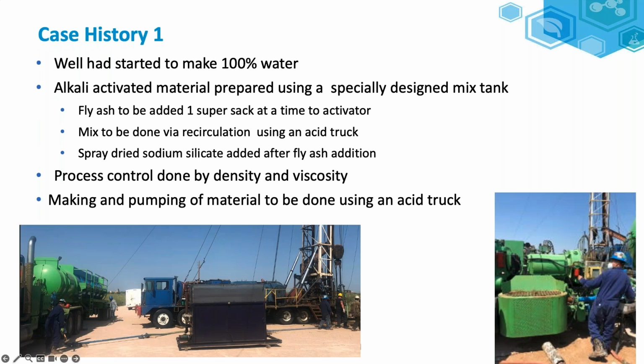The cost of the raw material was a bit more than a Portland cement. Where the savings was instead of using a pump truck, an acid truck was used for mixing it. So the operator had a mixed tank. The way the product was made was there was a silicate solution. The fly ash was added into the tank. It was recirculated via the acid truck. Once the viscosity got to the desired level, as well as the density, it was then pumped downhole via the acid truck. Next slide.